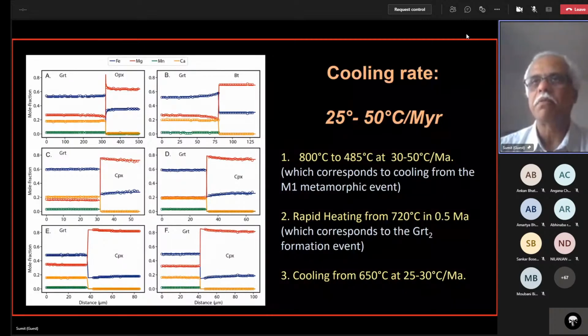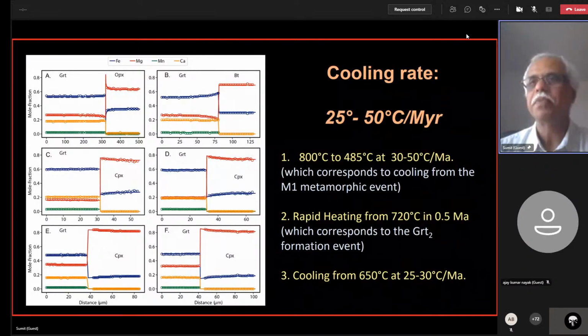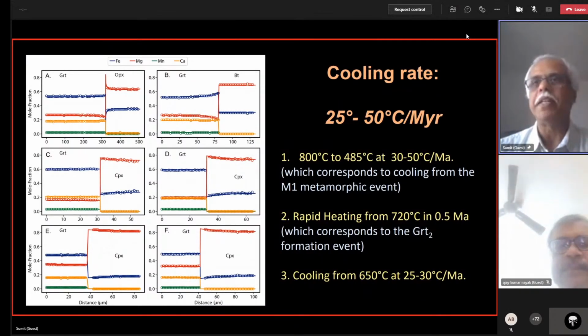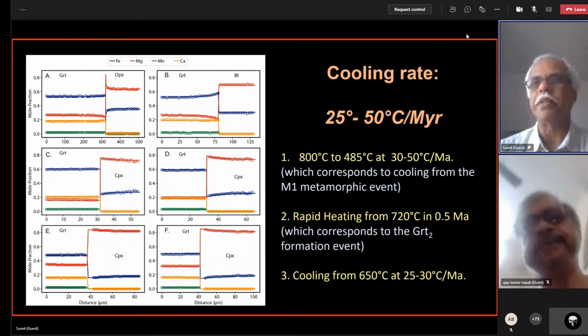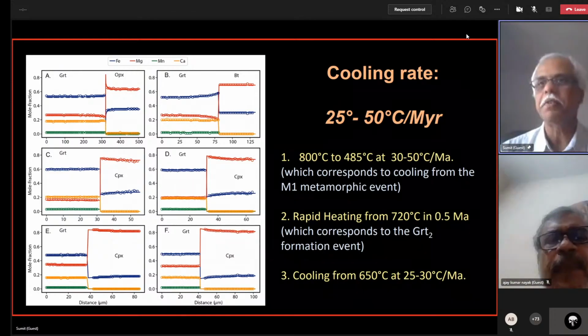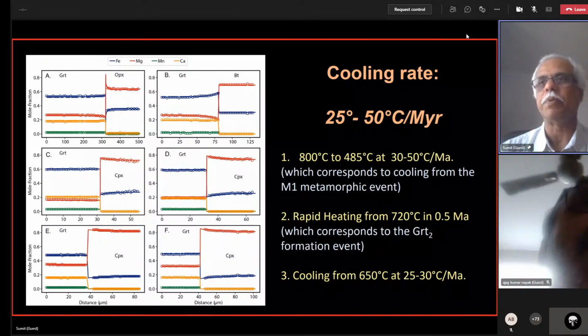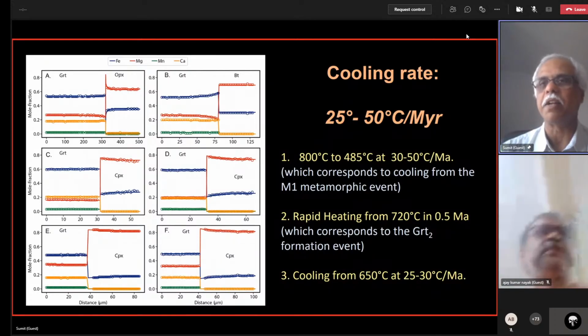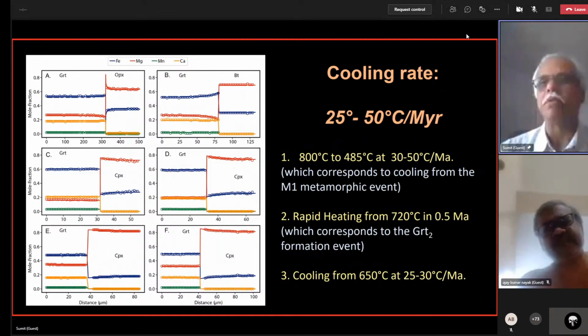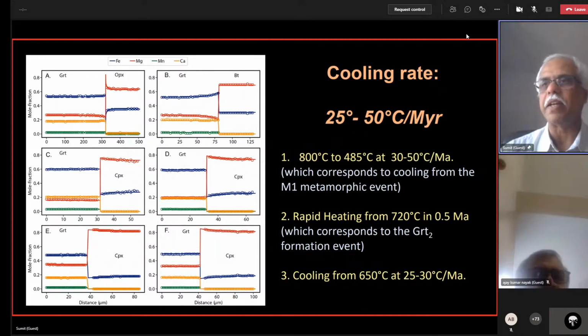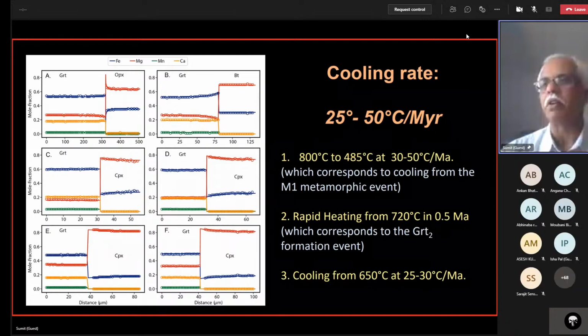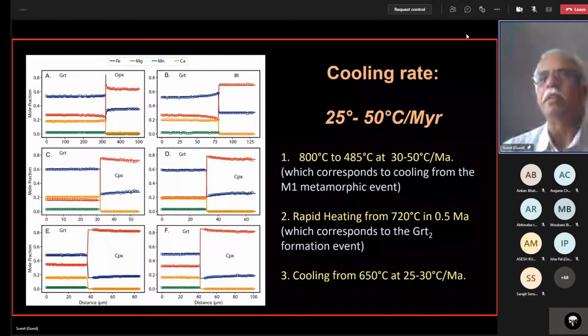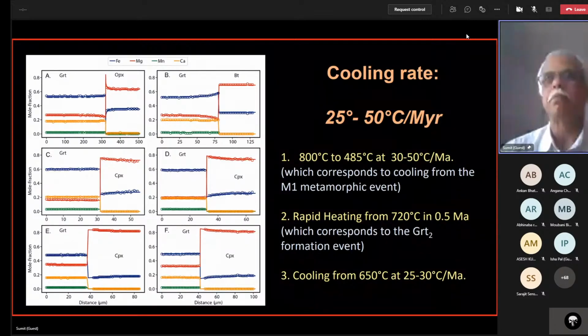This would be corresponding to cooling from the M1 metamorphic event. Now that is followed by a rapid heating again to 720 degrees centigrade over only half a million years. And this would correspond to the stage where you form that second garnet, the garnet 2. And then it cools down again from about 650 degrees at roughly the same rate, it turns out 25 to 30 degrees per million years. So overall, the cooling rates for these different stages are always between 25 and 50 degrees centigrade per million years.